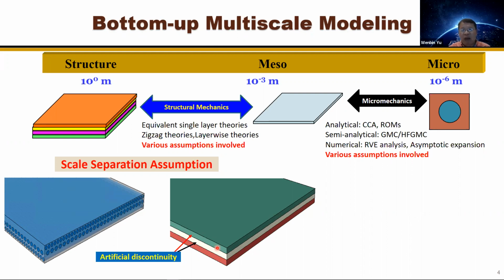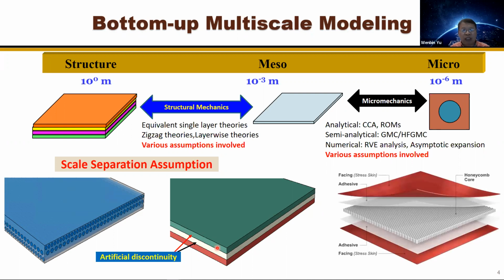But when you go to damage and failure, because damage and failure is a local phenomenon, then we have difficulty having a good prediction. And also for some situations, even the global behavior will be wrong. For example, we have a honeycomb in the middle, a sandwich structure with face sheets in terms of laminate. Then the traditional way, what we do is that if we use the bottom-up multiscale modeling, we take a unit cell, do a micromechanics calculation to get the material properties for that honeycomb. Then we treat it as a homogeneous layer to do a sandwich structure analysis. And it will have some issues even for the global behavior.